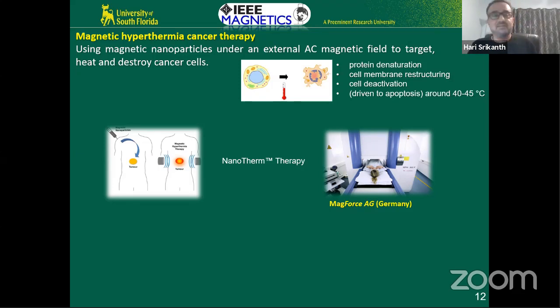And how do we do that? By this AC magnetic field, or AC magnetic hyperthermia. Now it turns out that there's one company that has commercialized this and is actually doing pretty well. They are doing a lot of testing. And this is a company that is based in Berlin. It's MagForce. And what they do is very simple. They inject it, and you can see that it's almost like an MRI machine, right? With the patient going into the magnet. So essentially, they take the particles to the tumor area, then turn on an AC magnetic field, and it locally heats the tumor, and it shrinks the tumor because the tumor cells are getting destroyed.